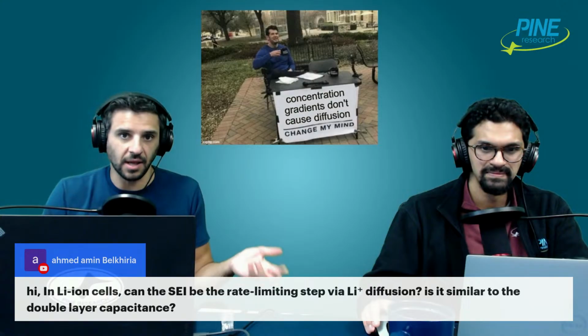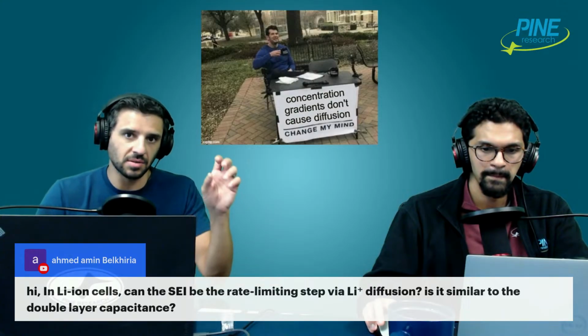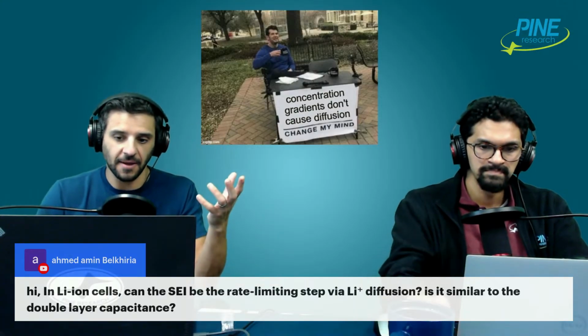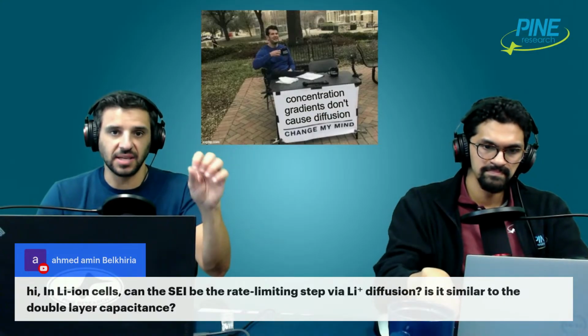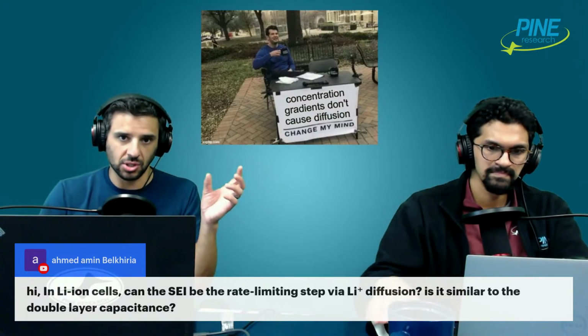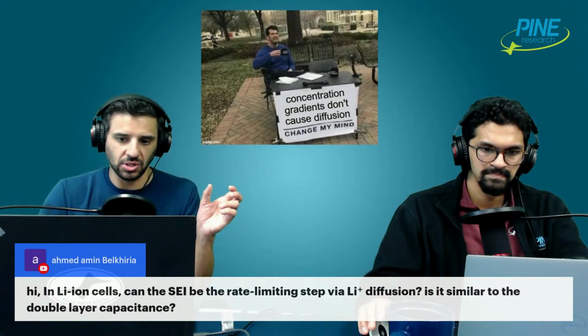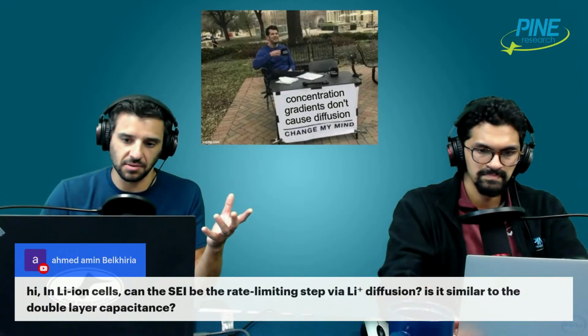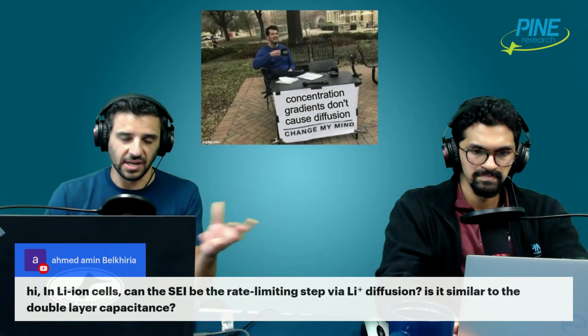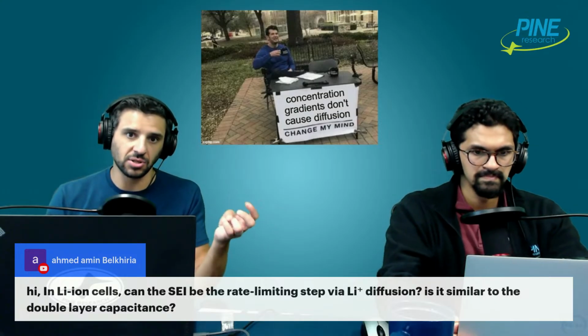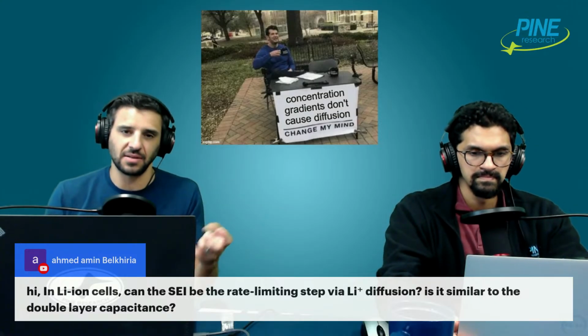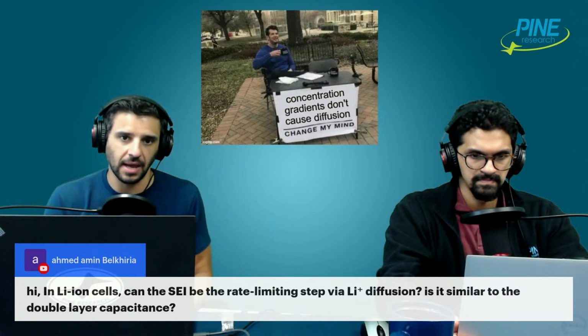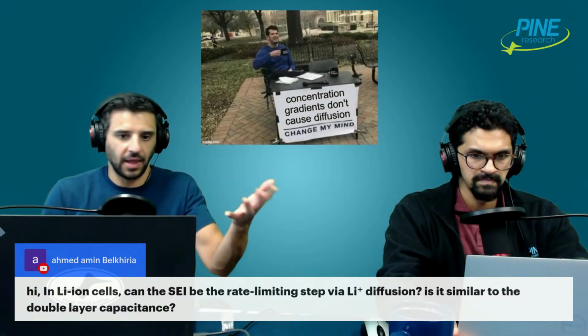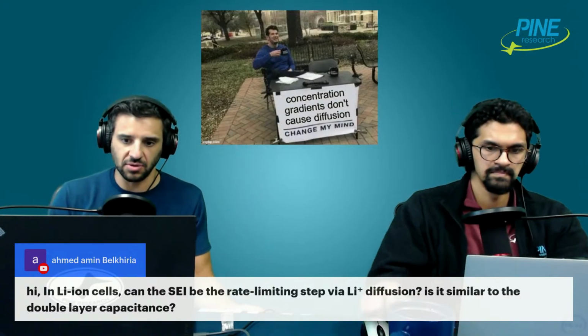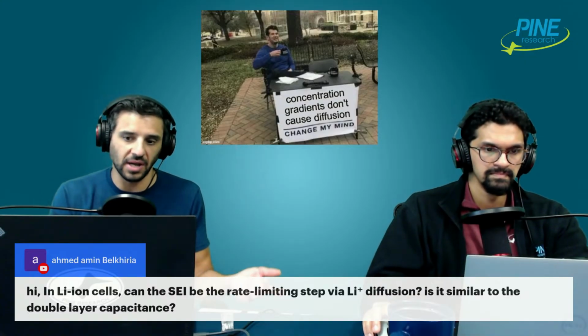But that is kind of what happens. It's weird. A little bit of the electrolyte has to decompose to form this film, the SEI, that then subsequently protects and allows the charge-discharge to occur, because otherwise the potentials at which you're charging and discharging, in many cases 3, 4, 5 volts or whatever, are enough that it would rip the electrolyte apart preferentially. But the SEI protects against that. You could think of it as slowing the kinetics of electrolyte decomposition down to nothing, such that the favored process occurs.